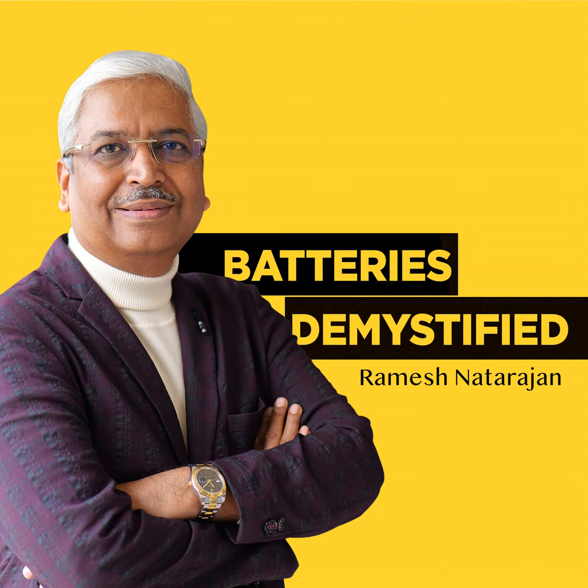The presence of metallic contaminants in the electrolyte can result in inaccurate outcomes. So we must take care to see that the electrolyte in which it is dipped is not having any contaminant. It is therefore recommended to verify the readings by measuring the overall voltage of the cell. The total cell voltage is determined by the algebraic difference between the potential of the positive plate with respect to cadmium and the potential of the negative plate with respect to cadmium.